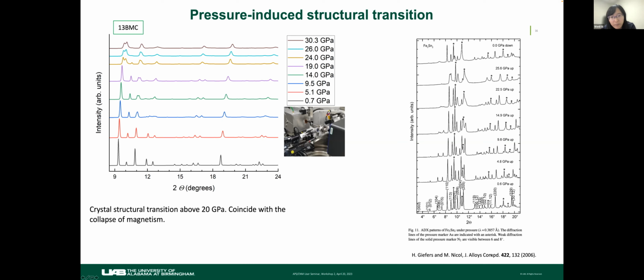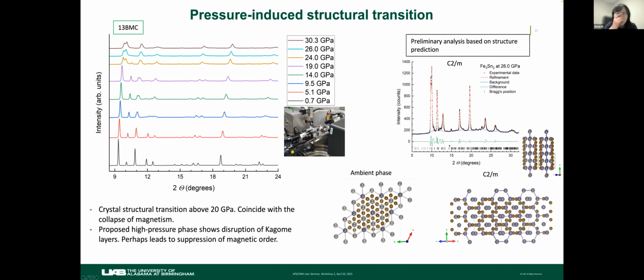And then we noticed there's an earlier paper from 2006 that also reported this. In this work, they did systematic studies on several compositions of iron-tin systems, and they did high pressure measurements on several compounds, and they reported a similar peak splitting and crystal structural transition under pressure, very close to the pressure we observed. However, they didn't identify the high pressure phase. So we worked with Yan-Sun Yao's group to identify the high pressure phase. He did some structural search, and we found that one of the C2/m phases could be a possible candidate for the high pressure phase.